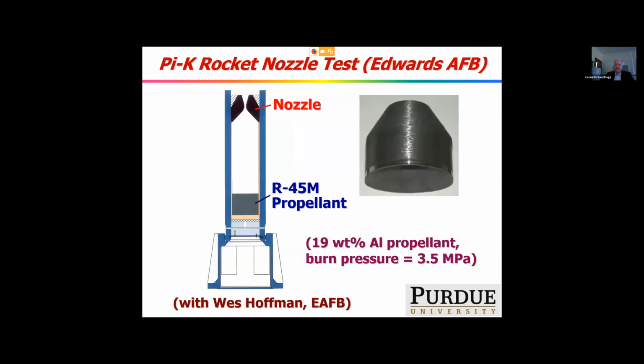So there's nothing like a real test to prove whether this is going to work in this application. So we were fortunate to be able to work with Wes Hoffman at Edwards Air Force Base. Wes took our rocket nozzle liner and surrounded it with a carbon composite. He did that because in the test it's upside down relative to a rocket. The propellant's on the bottom, the nozzle's on top. It's a nozzle liner, and so he wanted to make sure that the propellant went through the orifice and not around it, so he backed it with carbon just to fill space.